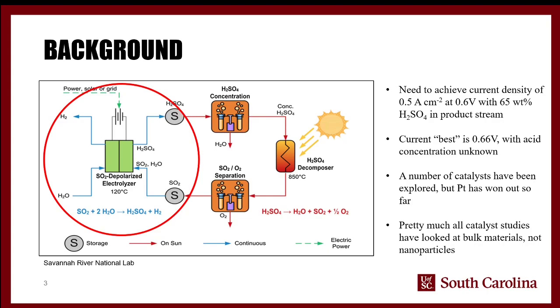And so to hit that with, again, a number of assumptions, you need to achieve a current density of 0.5 amp per square centimeter at 0.6 volts, and you need to produce a product stream of about 65 weight % sulfuric acid. The product stream needs to be that concentrated because that's what you need to have the decomposer step run efficiently. And so if you produce a product stream that has a lower concentration than that, you're going to have some concentrators before the actual decomposer. Any additional equipment is additional capital costs. It's an additional point of failure. And so that's a key thing: you want to be able to put out a product stream with an ideal concentration.